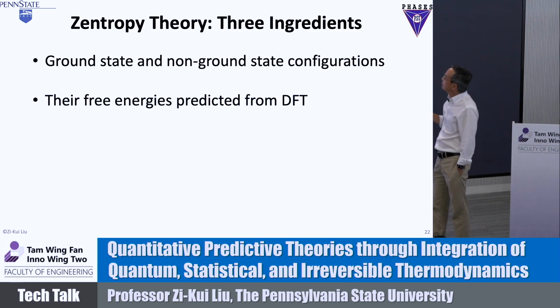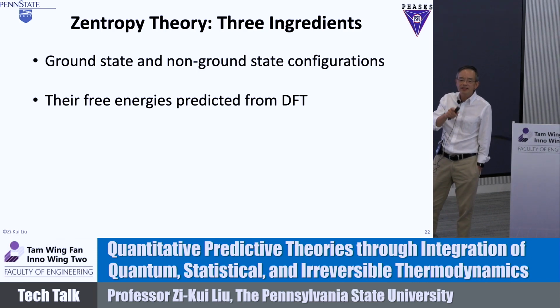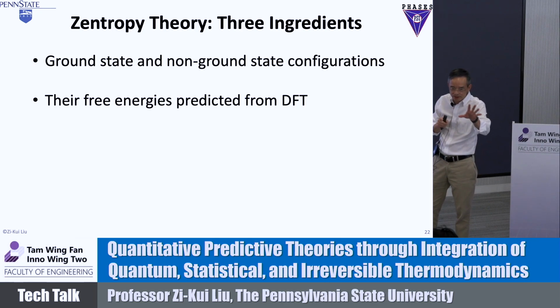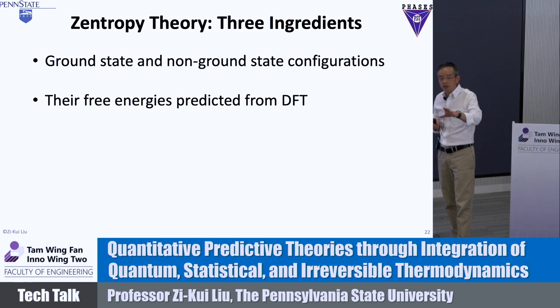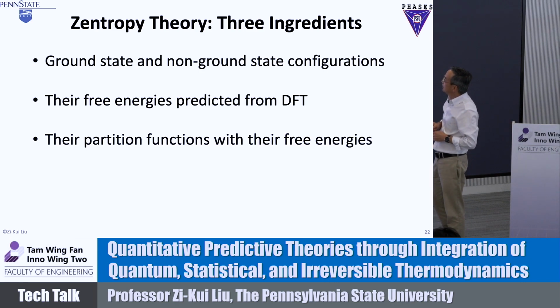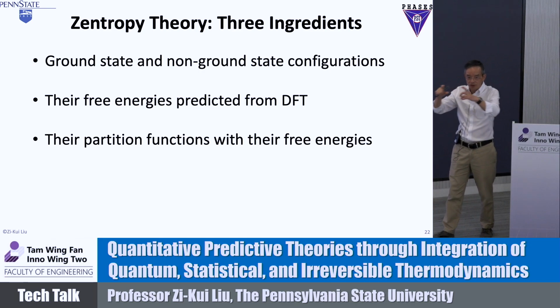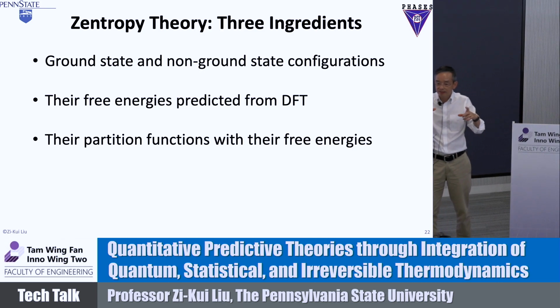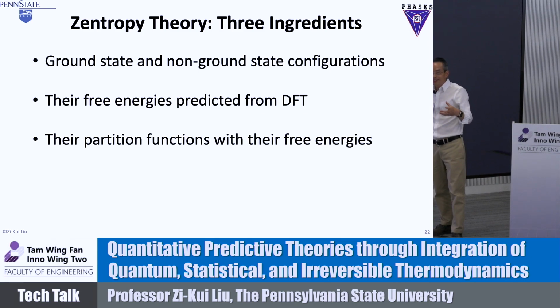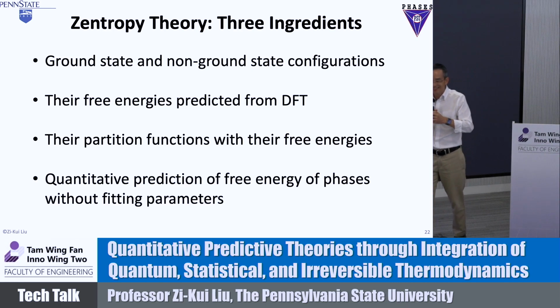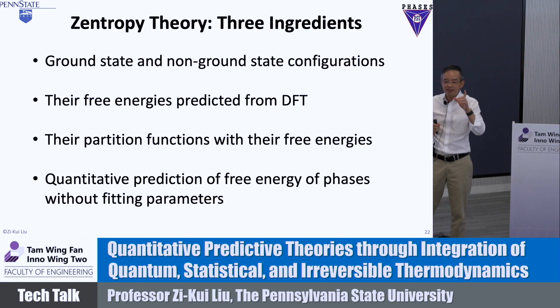That's the first one. Second one is that you cannot only fit into zero energy, you have to fit into the free energy. Okay, I think Suboshi told me you did that already. You have the force into the picture, right? The force, because you calculate the phonon from the force. If you have all the forces for all configurations, the last one is the sampling. You have to use the free energy to do the partition function sampling. That means when you talk about probability of each snapshot, you have to use the free energy of that snapshot to do the probability calculation. You have all three together. I hope you will demonstrate to me you can predict it. Okay? Your transition temperature will be less than 5 degrees disagreement with the experiment. Because that's very good, right?